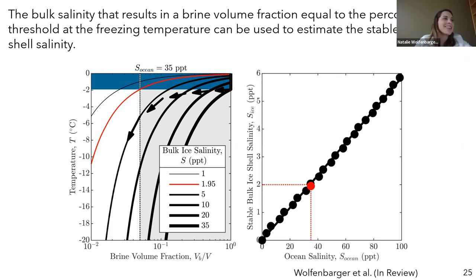What we can then do is scale this process to any ocean salinity, because all we're really doing is changing things like the freezing temperature of the solution, which here it's -2, but for an ocean salinity of 40 could be -3. Off the top of my head, I don't actually know. But the important part is when we do this analysis and we consider a range of ocean salinities, we end up with this almost linear relationship where this red dot here is basically this value here. And so this is actually, if you'll notice, the salinity of ice over the salinity of the ocean, which goes back to this quantity we were interested in initially of 0.058.